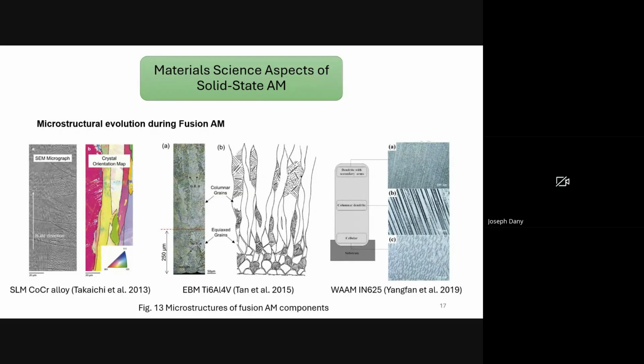One hallmark feature of fusion-based additive manufacturing is directional solidification, where the metal solidifies with strong anisotropy due to steep temperature gradients, driving epitaxial grain growth from the substrate or prior layers along the build direction. The resulting grains are typically elongated, columnar, and aligned with the thermal gradient, often forming cellular and dendritic structures. This famously leads to a strongly textured microstructure with 001 and 110 crystallographic orientations, commonly observed in FCC metals such as stainless steel or nickel-based superalloys, which strongly influences mechanical behaviors.